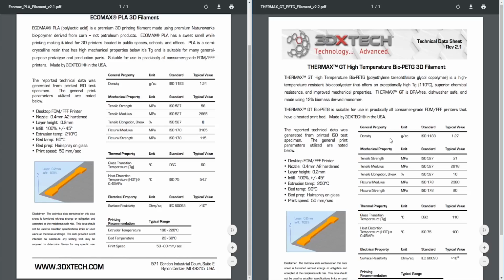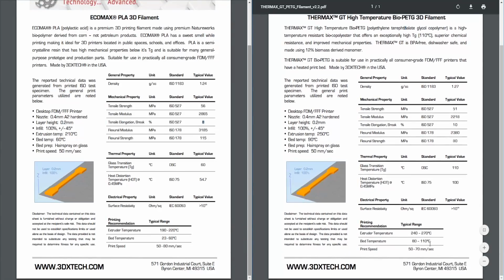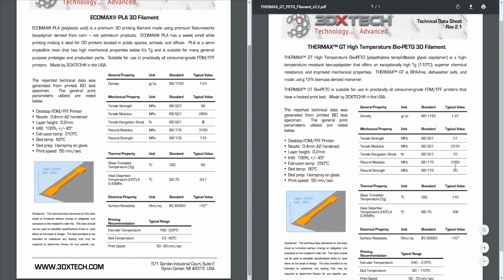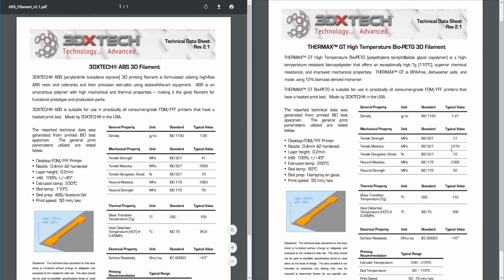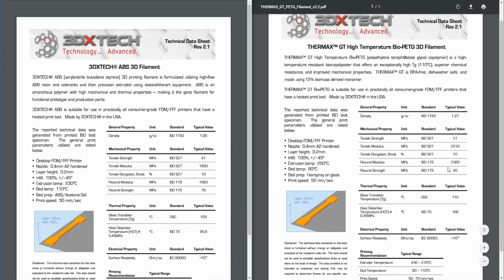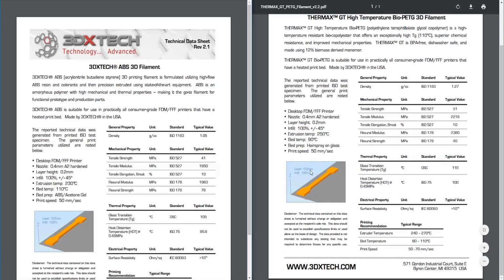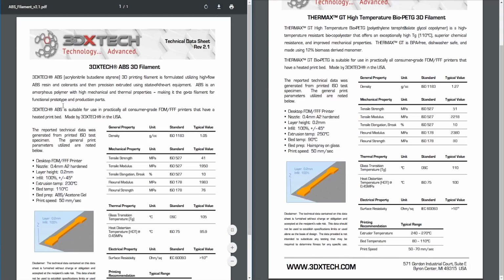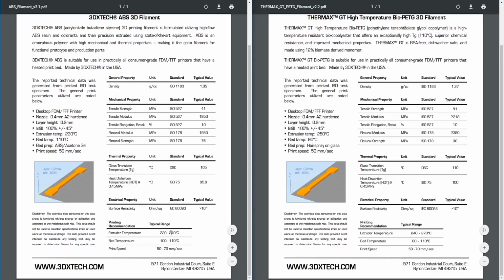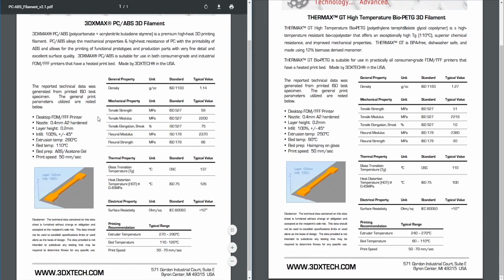It loses all of its strength for the high temperature. Definitely not as stiff here. Definitely not as strong. A little bit better, but that's like ABS. So basically you would use this to get it up to ABS's standards. So ABS: stronger, stronger, same flex, stronger, stronger. More print temperature, bed a little bit less. So this would probably be your ABS alternative if you could hit that extruder temp of like 240, a little bit over, 20 over the minimum there.